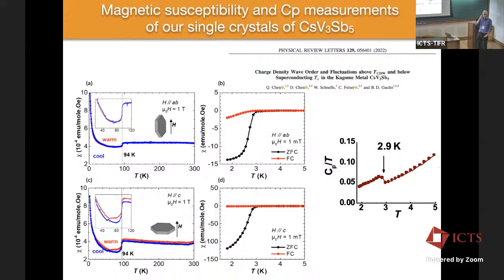It's at a little bit of a higher temperature than it was for the initial samples. It's about 2.9 Kelvin now instead of about 2.5. The bulk susceptibility measurements, though, look essentially identical to the original measurements published by Ortiz et al. And that is that at high temperatures, you got a very Pauli-like susceptibility, and then there's almost a step function at 94 Kelvin, and that's true whether the magnetic field is in the Kagome planes or perpendicular to the Kagome planes.